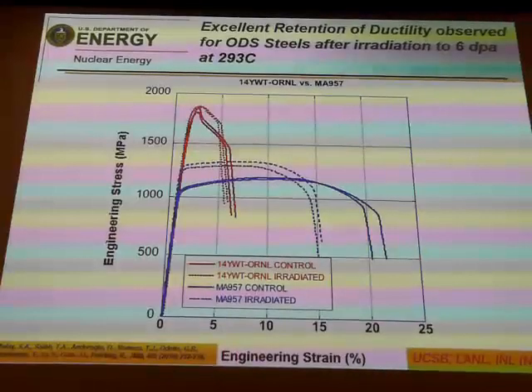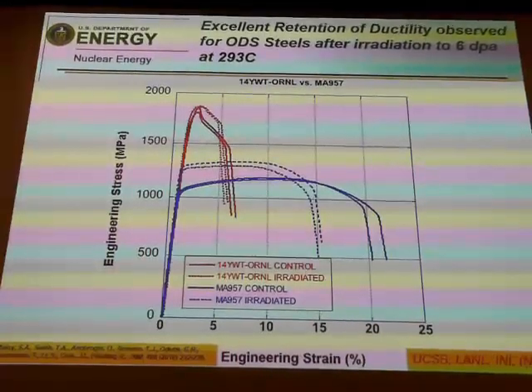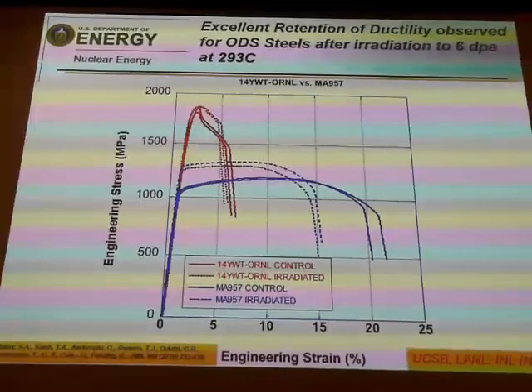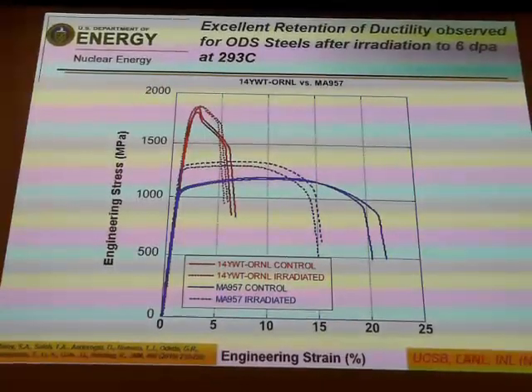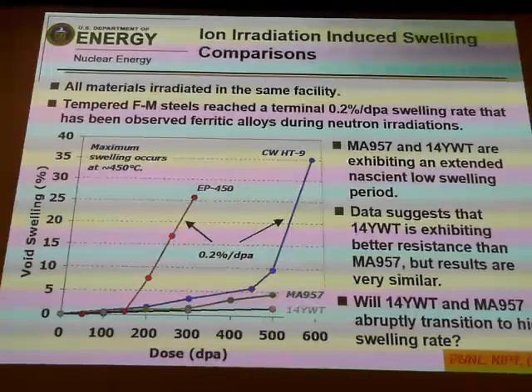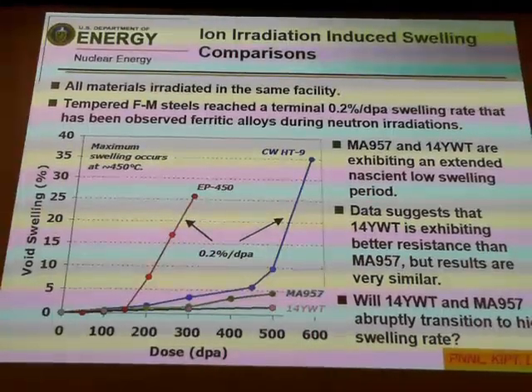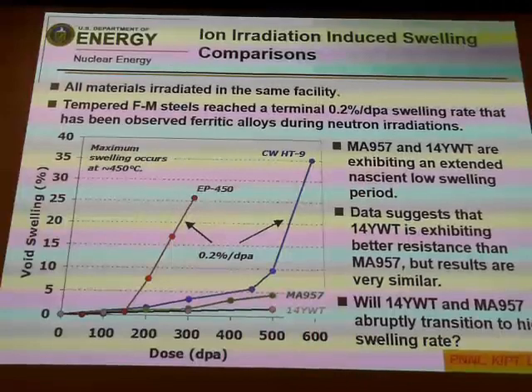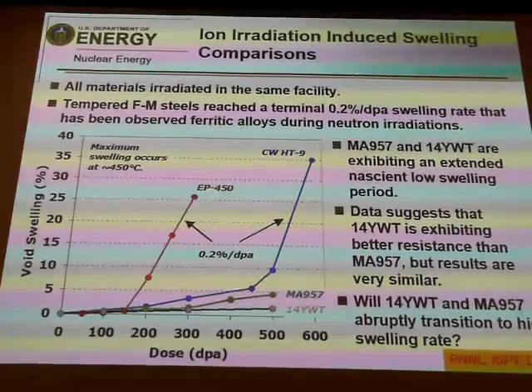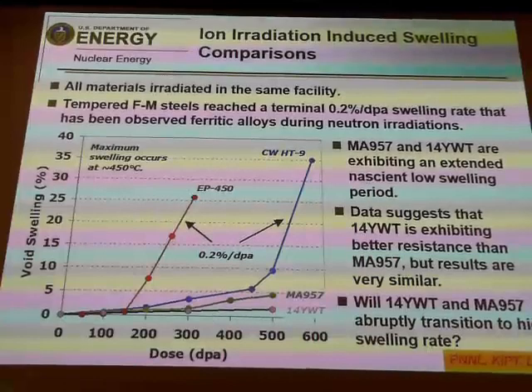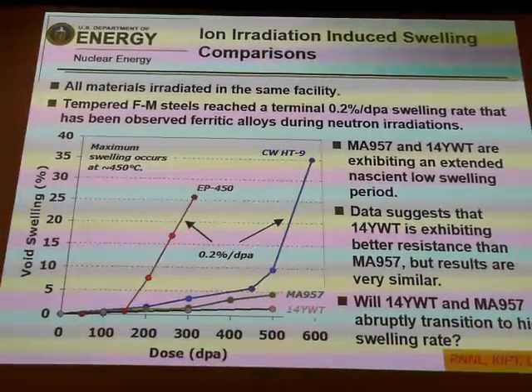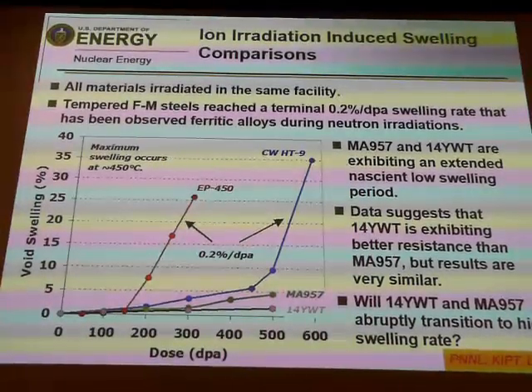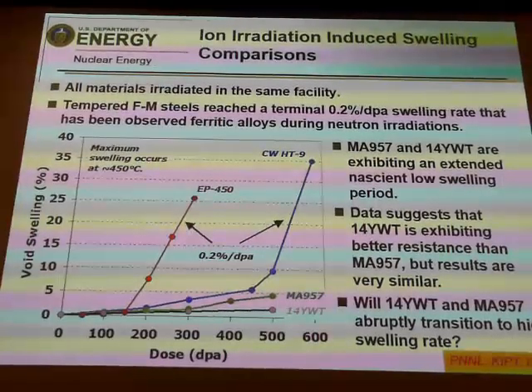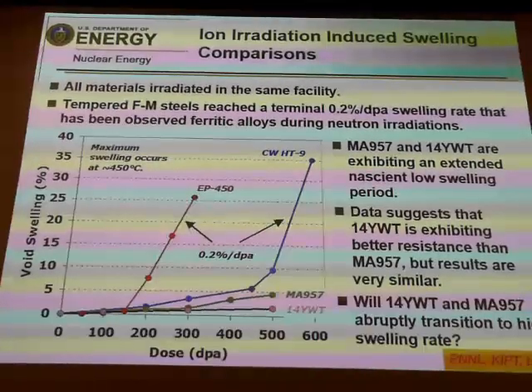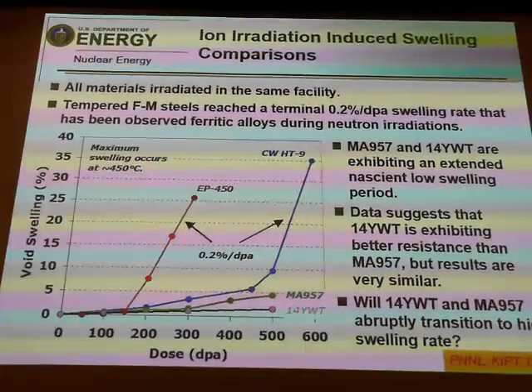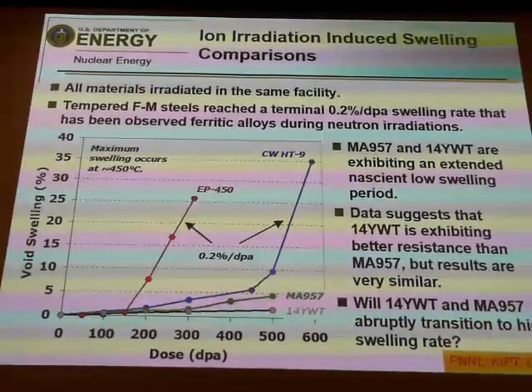It went up by about 200 MPa, unlike the ferritic martensitic steels, where the hardness increases by almost a factor of 2 after radiation. So it really does show promise, and through some high-dose ion irradiations, we've irradiated our 14YWT material all the way out to 500 dpa from ion irradiation at least, but compared to HT9, it's still not swelling yet. So it really does have a lot of advantages, but we still have a bit of a ways to go to get it to actual engineering forms.